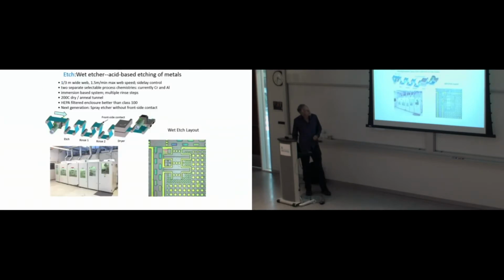Okay, so now here's something about the etchers. Again, you don't need this. This is more a function because we have roll-to-roll. We had wet etchers where things would go unwound and would go through a bath and then come out. We had a water knife so we had very precise timing of how long it was etching for, and then you shut the etching off because you don't want it to keep going. That would go into the water knife, which would kind of stop the etching, and then you'd do a rinse, and then you'd have a dryer.